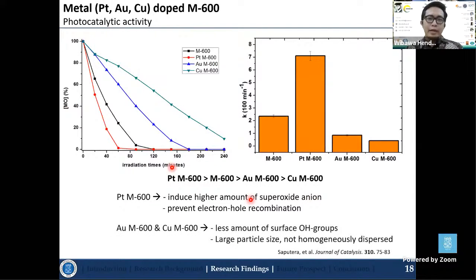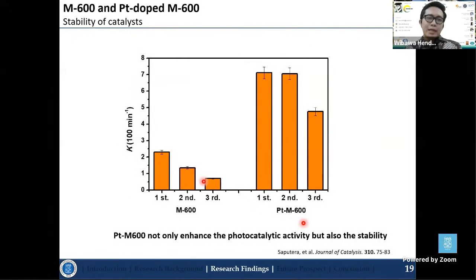However, for the gold and copper, it actually gives lower activity compared with the mixtures which were calcined at 600 degrees C. Maybe it is due to the large particle size, or the metals are not homogeneously dispersed in the titanium dioxide support. So based on the stability test, it can be seen that the platinum deposited on the M600 gives better stability compared with the M600, which actually decreased gradually with increasing reaction cycles.